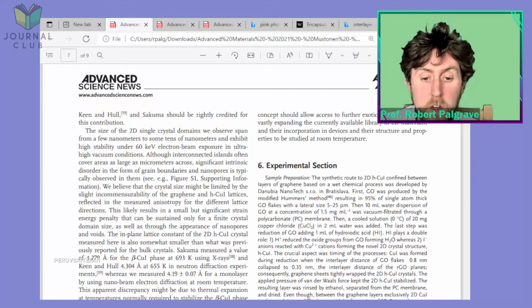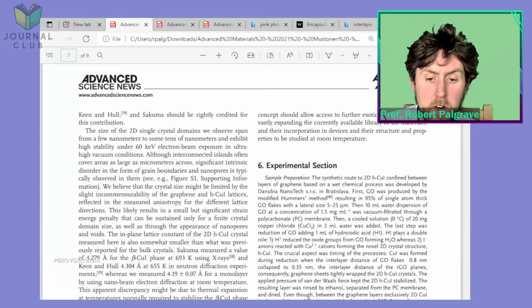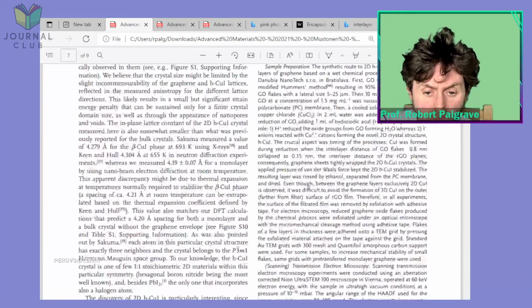Consequently, graphene sheets tightly wrapped the 2D hexagonal cuprous iodide crystals. The applied pressure of van der Waals forces kept the 2D hexagonal cuprous iodide stabilized. The resulting layer was rinsed in ethanol. Sorry, let's scroll down. Rinsed in ethanol.